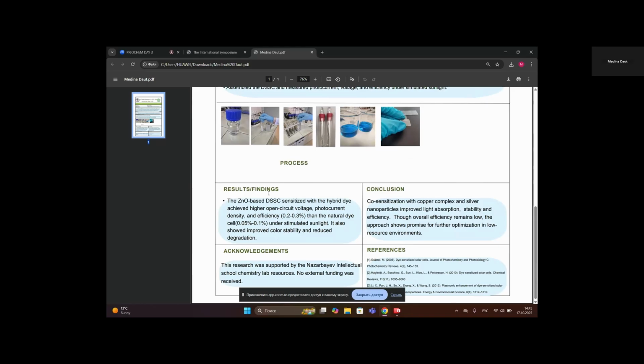So my results show that the zinc oxide-based DSSC sensitized with a hybrid dye achieved higher open circuit voltage, photocurrent density, and efficiency, from 0.2 to 0.3%, than the natural dye cell under simulated sunlight. It also showed improved color stability and reduced degradation. In conclusion, co-sensitization with copper complex and silver nanoparticles improved light absorption, stability, and efficiency. Though overall efficiency remains low, the approach shows promise for future optimization in low-resource environments.